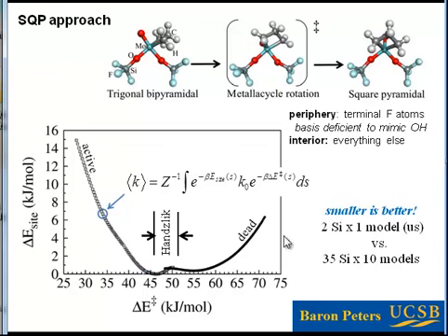Okay, here are the results. You see that the activation energy spans from 30 kilojoules per mole, really, really active. This is going to turn over really quickly, all the way to 70 kilojoules per mole, right? So this site is basically dead now, in comparison to that one, at least. And that's a really remarkable range, right? So the answer to this question, what if you tweak your model of the active site a little bit? Well, you can change a lot, right?